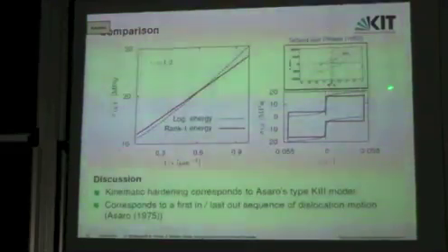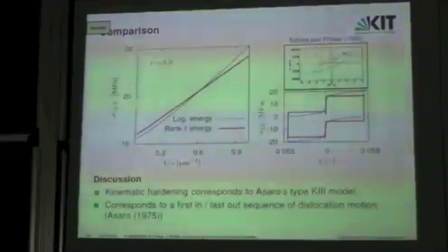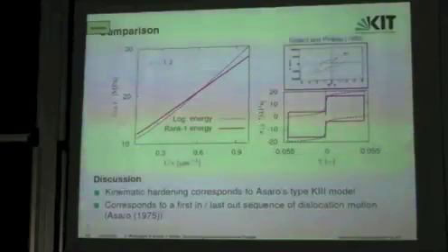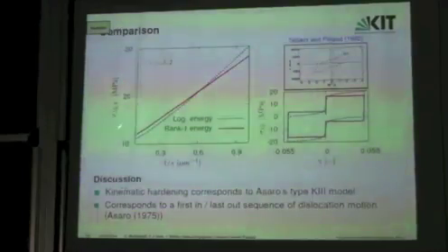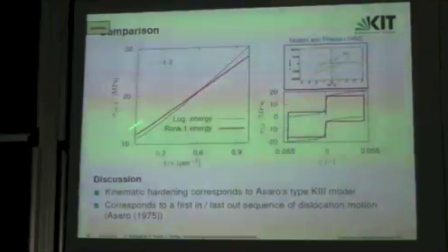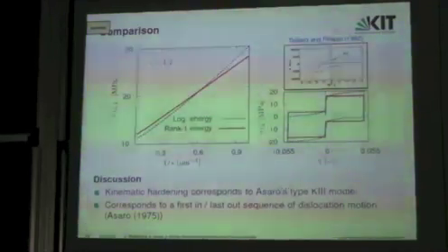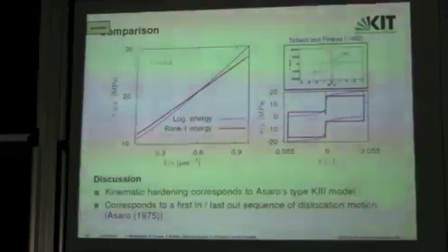Okay, we already saw these curves. So this is the cyclic loading curve, and some of the rest already discussed that this is also observed in experiments, so also quite an interesting result. And in order to compare these two energies, let's have a look at the scaling behavior. You see here the yield stress as a function of the size, and the scaling behavior is very similar in this application. Both scale roughly like 1 over S.